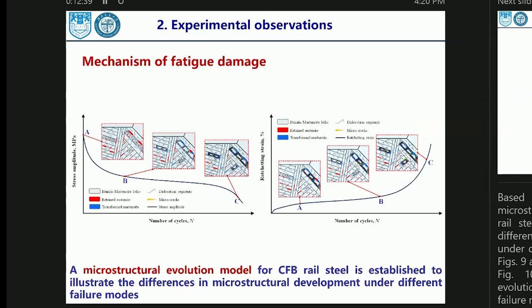So we conclude that under the stress controlled mode, that is, with the existence of ratcheting strain, the microstructure evolution is different from the traditional strain controlled one. Mostly, the ratcheting strain accelerates the dislocations and substructures, and the martensite transformation happens more easily under stress control. Of course, this microstructure evolution mode is concluded with the evidence of other experimental observations, and I don't show them in this presentation.